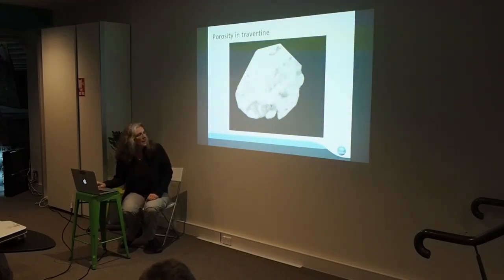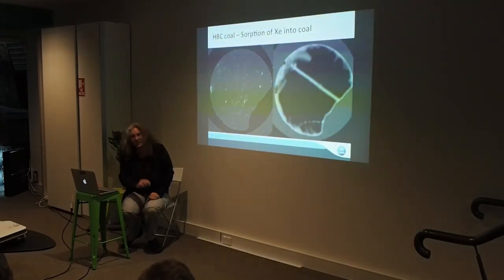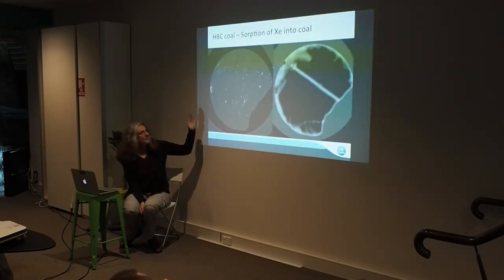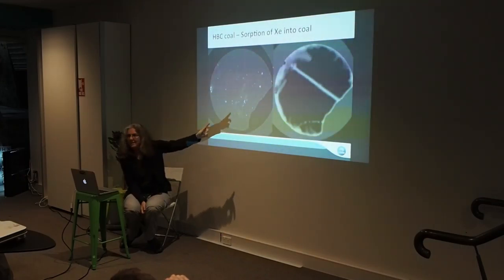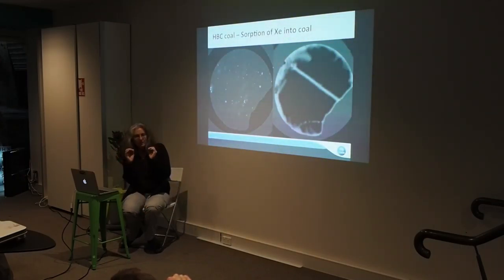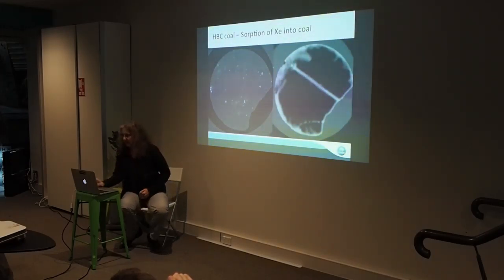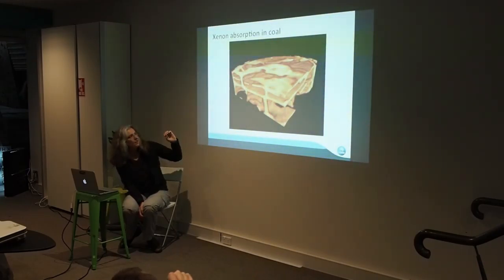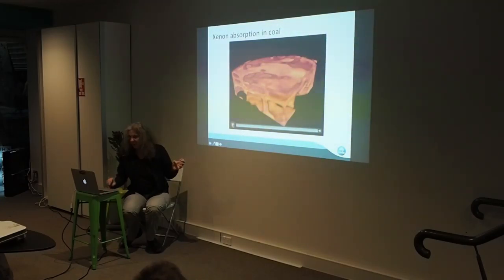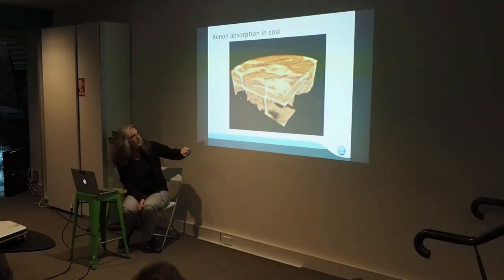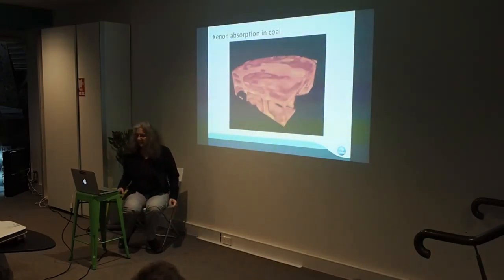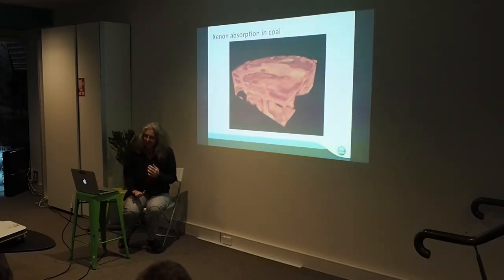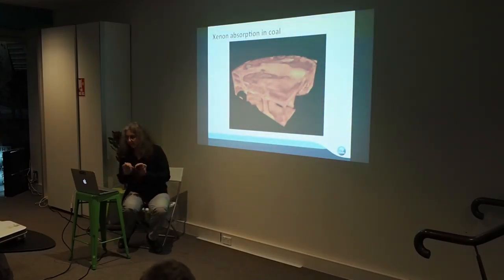However, in coal that's not the case. This is a cross-section of a coal sample — on the left is the sample image and on the right is where the Xenon gas went. It diffuses into holes far too tiny to see, but we can see they're there because of the Xenon. This is actually what I was doing two days ago. With the rendering of the Xenon on its own, we can see how the stuff diffuses into the coal over time — that's actually over three days. Then at the end I turn on the CO2 tap and it flushes the Xenon out. The reason people are interested in that is carbon sequestration and using CO2 to push out methane — they need to know how gas moves through coal.